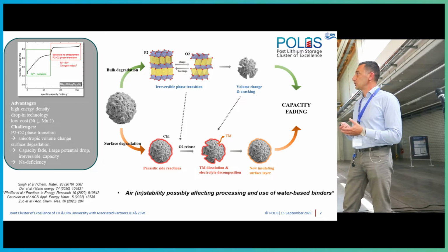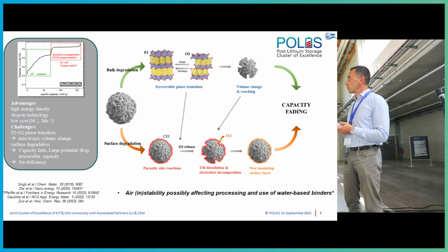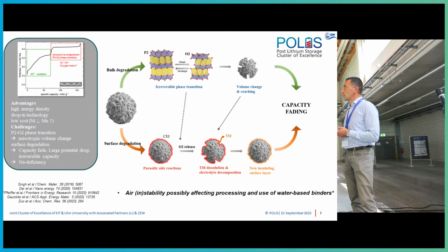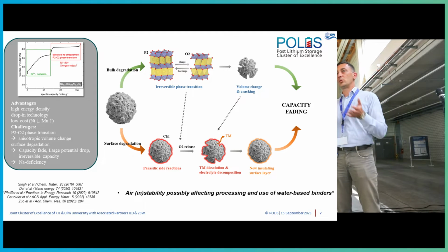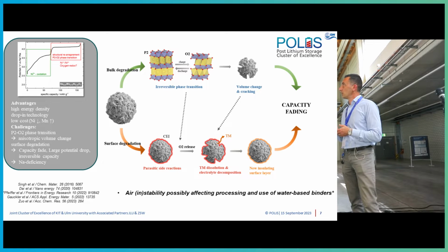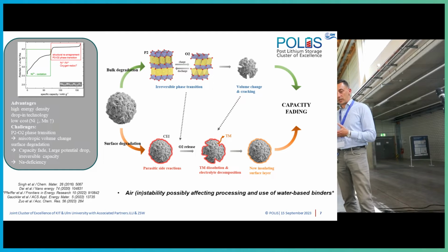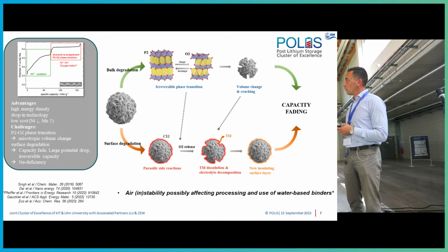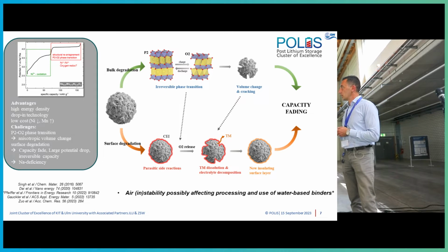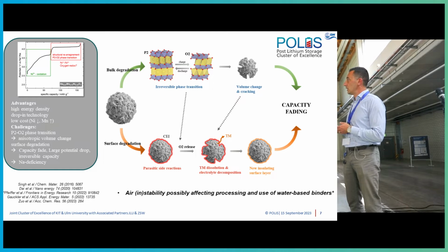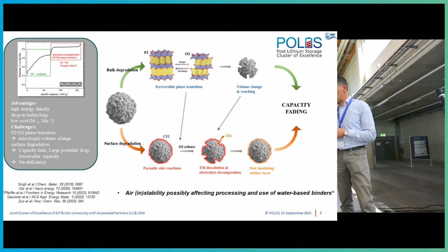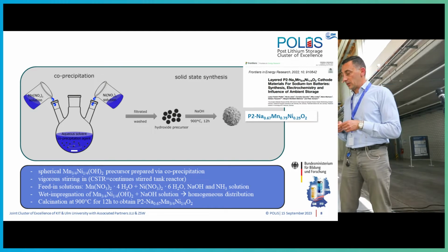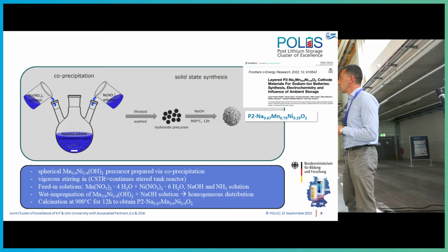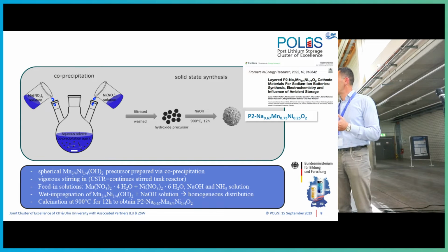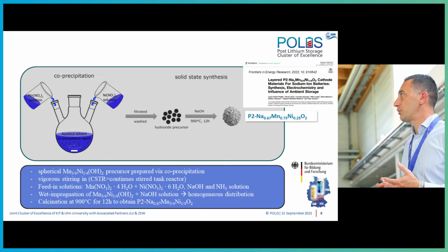What are the problems of P2 layered oxides? One problem has to do with bulk degradation, and this is exactly what I just said: the phase transition from P2 to O2. This leads to relatively high volume change and eventually cracking. Another path is surface degradation, where we have side reactions, transition metal dissolution, oxygen release, and the creation of a new insulating surface layer. So when we started working on the sodium manganese 3/4 nickel 1/4 oxide, we looked into a synthesis that could be scaled up.